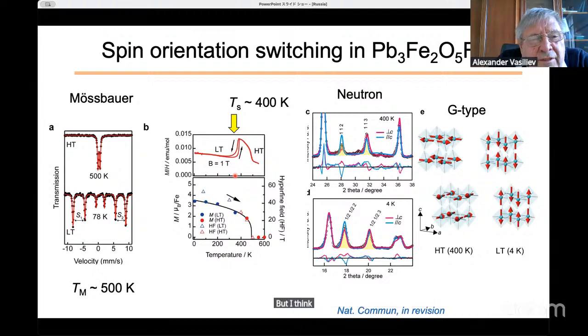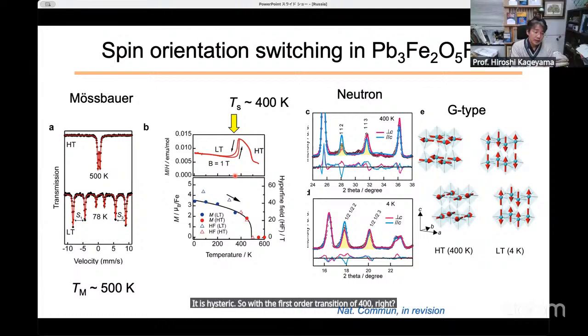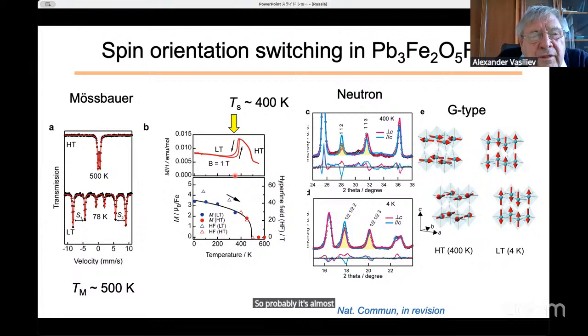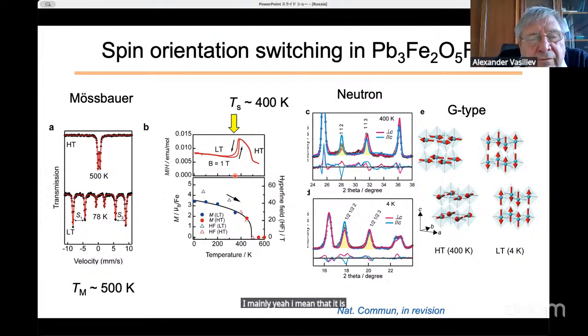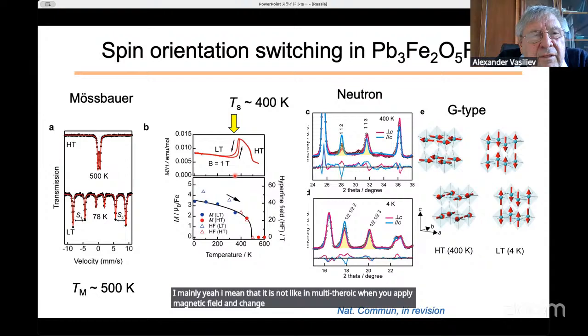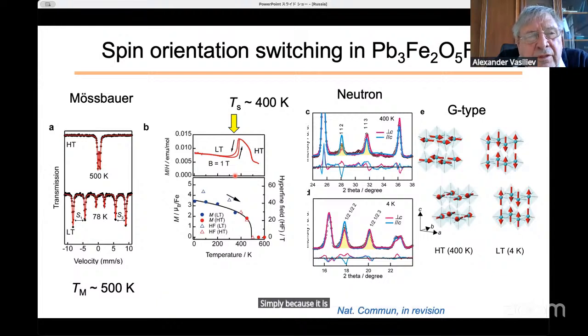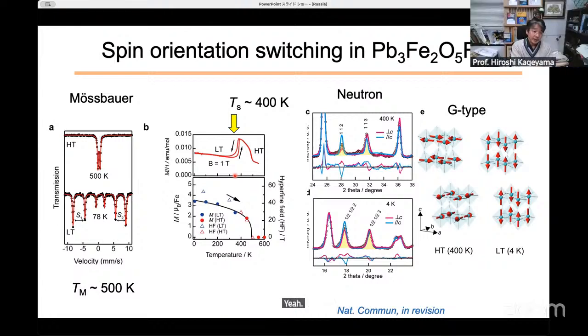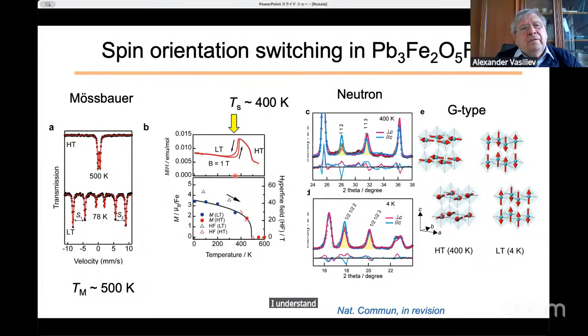I think that it is a first order transition at 400 Kelvin, and you cannot influence it significantly by an external magnetic field. It is hysteretic. So the first order transition at 400, right? Yeah. So probably it's almost impossible to influence it by an external magnetic field. For the electric properties, I mean that it is not like in multiferroics when you apply a magnetic field and change the electric permittivity. In this case, probably nothing like that will happen, simply because it is a rigid first order structural transition. But I agree, the major problem is that we only have a powder sample. Okay. Yeah.